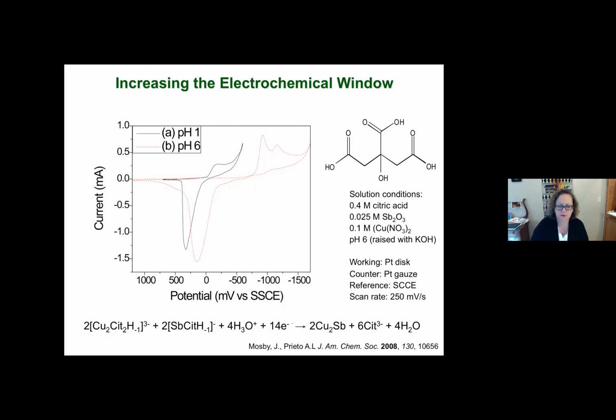The cyclic voltammogram I'm showing on the left, in black, is the CV scan for these two metals in solution at low pH. The problem is that at potentials approaching about negative 400 millivolts versus SSCE, you see the evolution of hydrogen. And so you never get to a potential negative enough to be able to plate antimony.